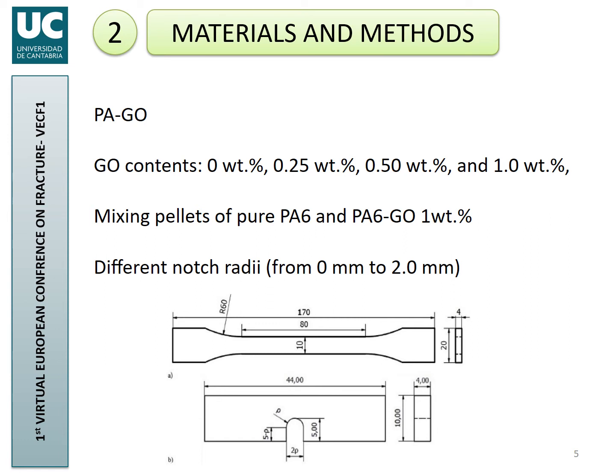material pellets had the graphene oxide already dispersed in the material, and this dispersion was developed and ensured by the material producer. To obtain, for example, the 0.50 weight percentage material, you just have to mix 50% of pellets of pure polyamide and 50% amount of 1 weight percentage material, 50-50. If you want a 0.25 weight percentage material, you have to mix 3 parts of pure polyamide and 1 part of 1 weight percentage material.